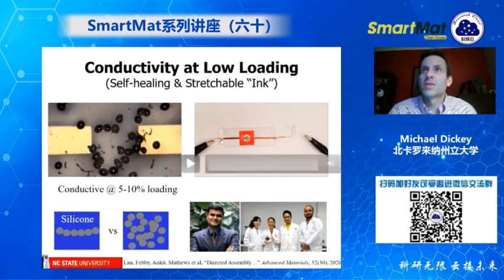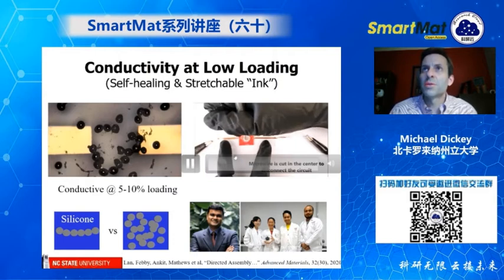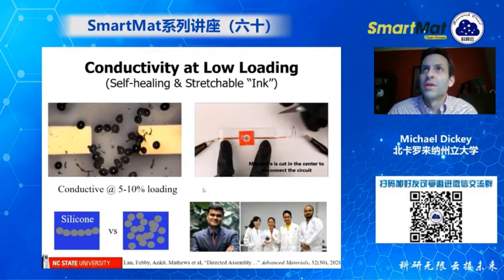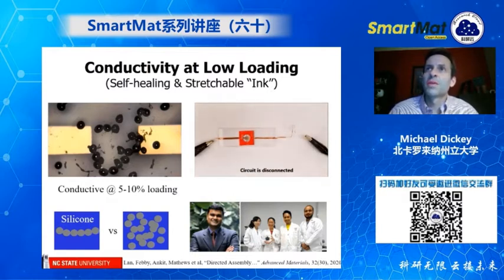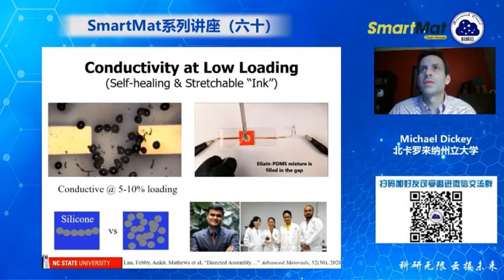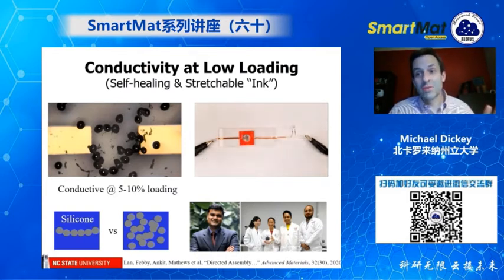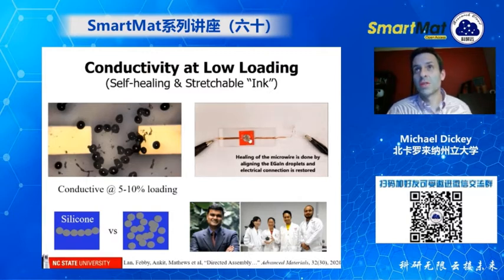The other interesting thing is you can make a self-healing ink. So this is a very simple circuit. We literally cut it so that it's not conductive anymore. So we cut the silicone out, pull it out, and then we backfill it with this ink, which is just liquid metal in silicone. And you can see it goes in there. It's not conductive. Remember, it's at low loading, but if you apply the voltage, you can get the particles to line up. The circuit becomes conductive, and then you can cure the silicone, which will cause it to heal. So this was done with Professor Matthews and some really wonderful students from Singapore that came and visited my lab.